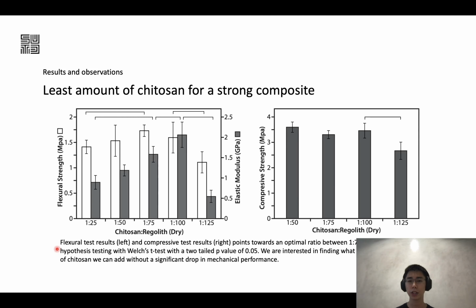Now, from these two results, what we concluded is that for the subsequent tests, the optimal ratio without compromising on mechanical properties should be within the range of 1:75 and 1:100. And for the sake of workability, we focus on 1:75 for the rest of the application.